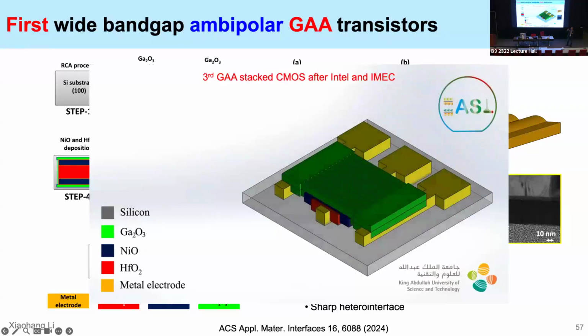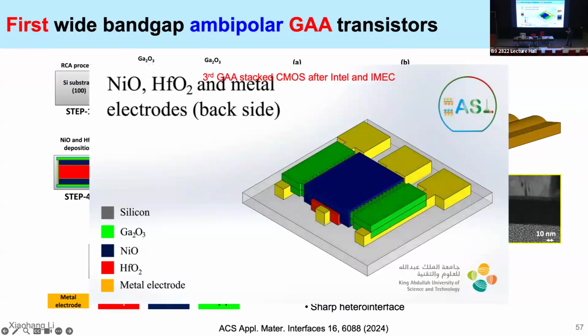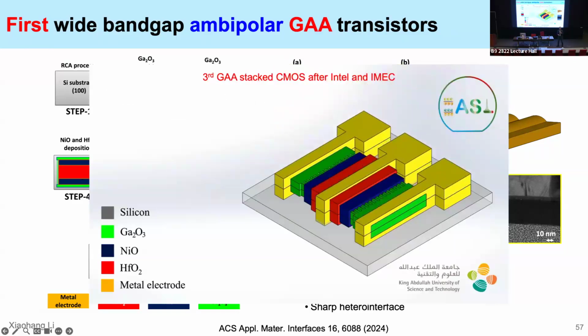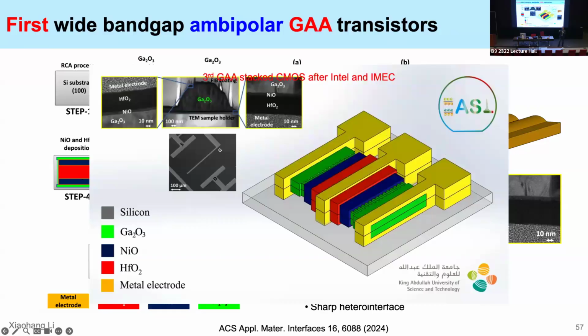And we flip it, remove the silicon substrate, and then put the dielectric and metal on the backside because we want to develop the so-called gate all around transistor. We want to have the gate around the channel so that we can have better control. By the time of the publication, I believe that we are the third organization after Intel and IMEC that reported the gate all around stack CMOS.